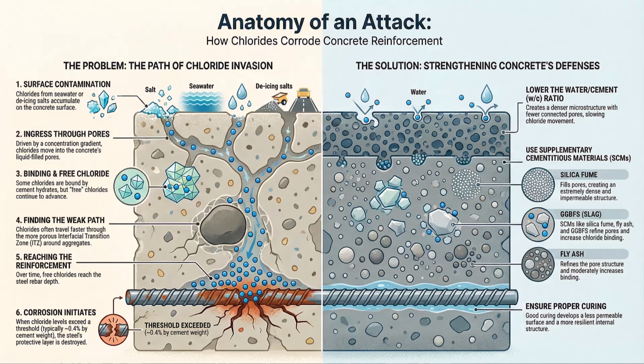What about physical protection? The cover depth over the steel, that's the final sacrificial layer, isn't it? It is the last line of defense, and in these environments, the cover requirements are significantly higher than global norms. Minimum cover is required to be between 50 and 75 millimeters, but the recommended value for a 100-year service life in a splash zone is 60 to 75 millimeters or more. You're giving the chlorides a huge head start before they can even reach the steel. It buys you decades of time.